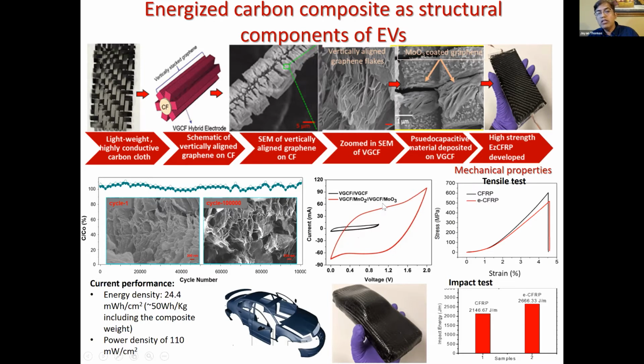And when you add this type of pseudo-capacitive materials, what you can get is a highly enhanced storage capacity. You know, this is a cyclic voltammetry, where the current versus voltage area gives you the energy storage ability of your device. You can see once you deposit other transition metal oxide onto the surface of this graphene, you can highly enhance the storage capacity.